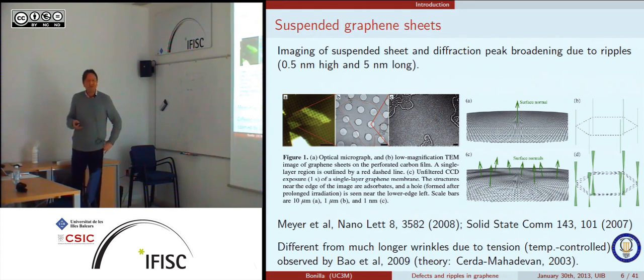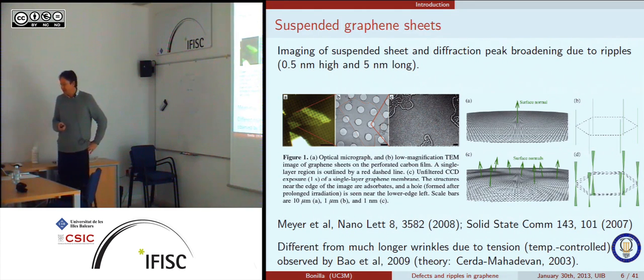So you can image the atoms in graphene by doing the following. You take one monolayer of this graphene, which in the early work was done by mechanical procedures like exfoliation of graphite. Then you put it on a carbon sheet with round holes, which are about 1 micron in diameter.